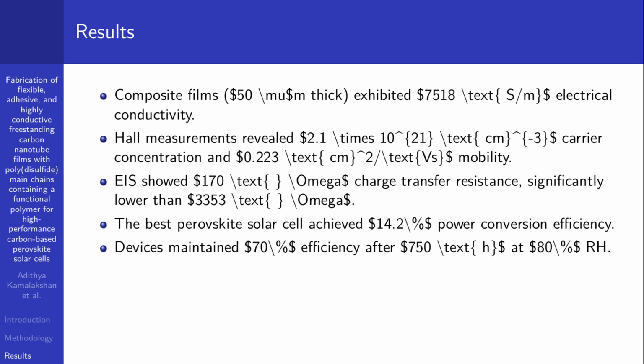Electrochemical impedance spectroscopy showed a significantly lower charge transfer resistance of 170 ohms for our electrode compared to 3353 ohms for commercial carbon paste. The best performing carbon-based perovskite solar cell achieved a power conversion efficiency of 14.2% with a short circuit current density of 22.2 milliamps per square centimeter, an open circuit voltage of 1.04 volts, and a fill factor of 0.62. This efficiency is only 4% lower than gold electrode devices. External quantum efficiency peaked at 50% at 550 nanometers.